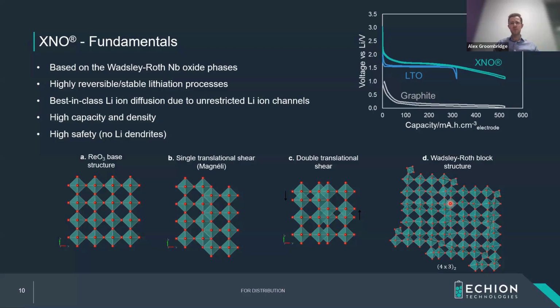And because of niobium chemistry itself, you can see in my diagram in the top right, this is half-cell performance of lithium titanate compared with graphite, compared with niobium XNO here. You can see the voltage is a lot higher, but a lot more capacity can be extracted because niobium has 2 redox from 5+ to 3+.